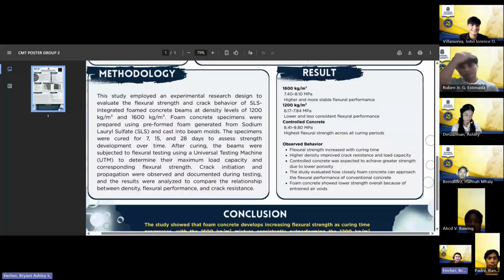Thank you, Mr. Padre. So, for the results of the experiment, 1,600 kilogram per cubic meter foam concrete showed a higher flexural strength, ranging from 7.40 to 8.10 megapascal, compared to the 1,200 kilogram per cubic meter foam concrete, which only achieved 6.17 to 7.84 megapascal. When we compare the strength of these two different densities of foam concrete to controlled concrete, the controlled concrete still produced the highest flexural strength, ranging from 8.41 to 9.80 megapascal.